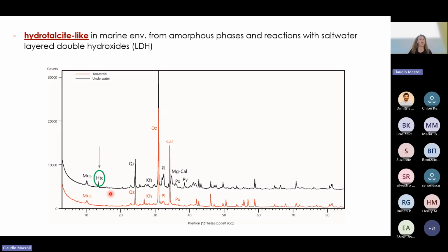So diffraction data show us the same as before. We used two different sets of samples, one from a land and the other one from an underwater environment, same type of material, linked together. They have the same composition originally, but they experienced different post-depositional environments. We have hydrotalcite present only in the one from the underwater site. Specifically, this is a case study from southern Italy, from Puglia, and it is a cargo of amphora.